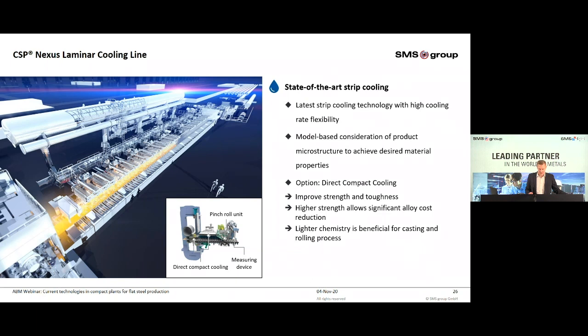Even more beneficial is the direct compact cooling. As shown in the picture, the system is positioned directly after the last mill stand. This leads to even higher improvements in strength and toughness, and as a result, in higher savings of alloying costs. Another benefit is a lighter chemistry in the casting and rolling process, because the strength is set at the laminar cooling and not only by the alloying elements.